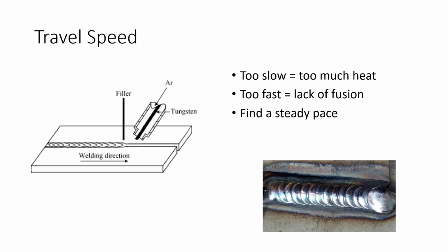Travel speed, this really comes into play when we are welding things up that have heat input problems, or the material needs to have a specific amount of heat input. So you need to put the right travel speed in so we don't put too much thermal energy into the material and then change the mechanical properties of the heat affected zone and or get weird stuff going on with the base material. So if we travel too slow, we're going to put too much heat into the material. If we go too fast, we're not going to get fusion. So if you are TIG welding, you're going to have to find a steady pace and go with that steady speed.